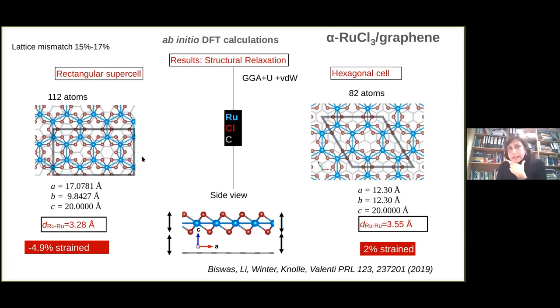And what you can see here already is that by bringing these two systems together, because there is a strong lattice mismatch between the graphene layer and the ruthenium trichloride layer, I'm going to have effects of strain on the ruthenium, mostly on the ruthenium trichloride, because it's more soft than graphene. And where I want to focus your attention is in fact on this hexagonal cell, because this is the cell where we find the system to be most stable.